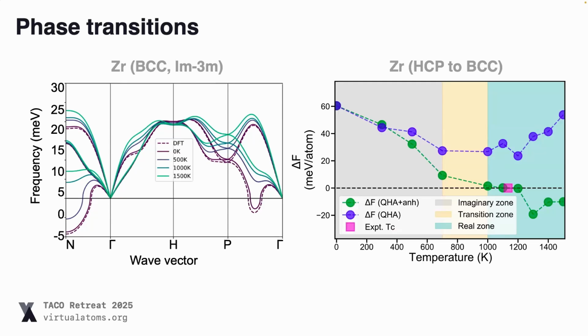The other nice thing that we can get, because we're getting temperature-dependent phonons, is we can have a look at phase transitions. And so here we're looking at zirconium in this BCC structure, and you can see that as you increase the temperature, your soft mode renormalizes, and at some point it becomes real rather than imaginary. And if we compare that point to the experimental transition temperature, you can see that we're within 200 Kelvin, which is actually not super bad for this material, especially, again, considering all the functional choice and things like that.